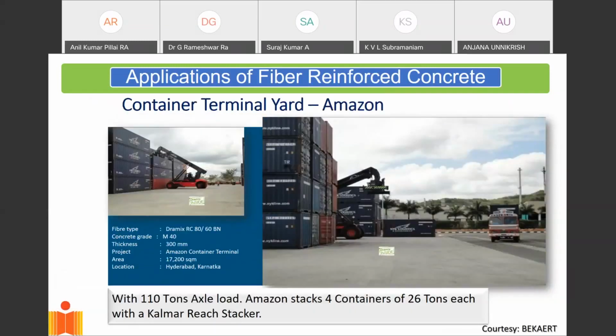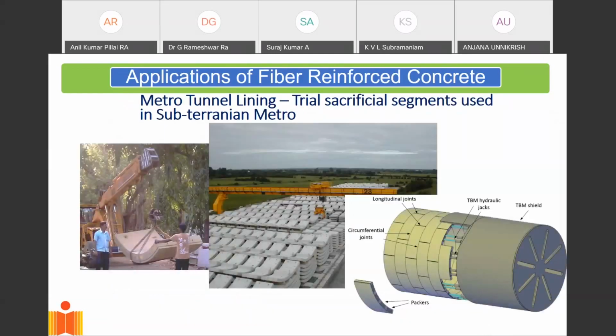Now, the other use of fiber reinforced concrete is in jointless pavements, and these are done for container terminal yards, where extremely heavy loads are piled onto very small areas of concrete. And these are large spans of concrete slabs without joints. And the only way we can keep the slab from cracking, and those cracks from opening and becoming wide, is by incorporating fibers. And now design procedures for the use of these fibers in these pavements are also being standardized so that they can be used. And a live example of this is the container terminal yard of Amazon, which has been designed for super heavy loads. And it's essentially one big jointless pavement made with steel fibers in concrete. Another use is metro tunnel lining, where the precast elements are now being reinforced with fibers instead of conventional reinforcement.